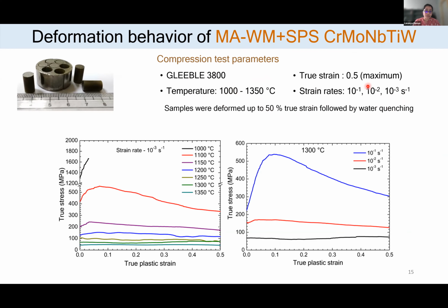For the mechanically alloyed composition, we did compression studies using Gleeble, which is a thermomechanical simulator. We did compression tests in the temperature range of 1000 to 1350 at different strain rates. After the completion of the test, all the samples were quenched immediately in water so as to retain the deformed microstructure. So these are the stress strain graphs. At 10⁻³ strain rate, at all test temperatures, the alloy showed a 50% compression ductility. One important thing to note is that at lower temperatures, the alloy has a peak hardening followed by softening, whereas at high temperature, it shows a steady state behavior.